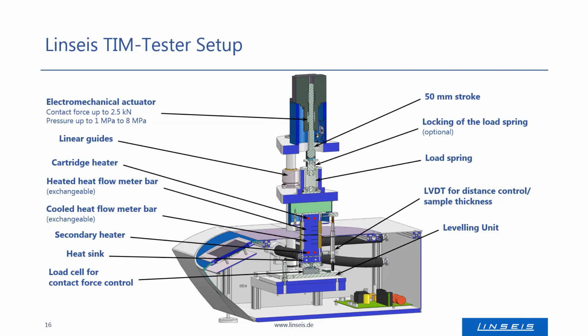We have an electromechanical actuator here on the top. This one can be software controlled and allows us to apply a variable contact force of up to 2.5 kilonewton. This translates into a surface area depending pressure of up to 8 megapascal.